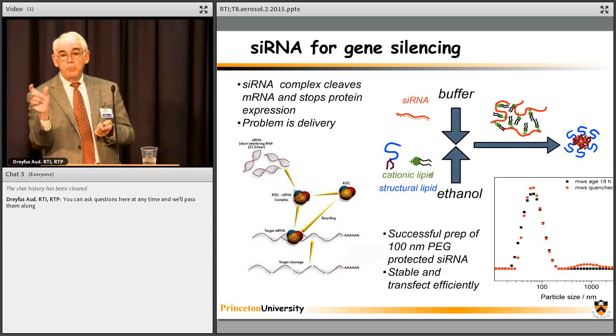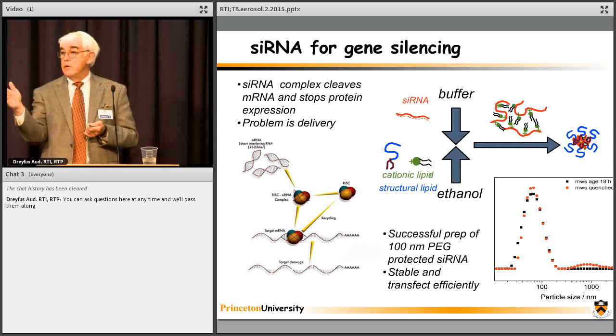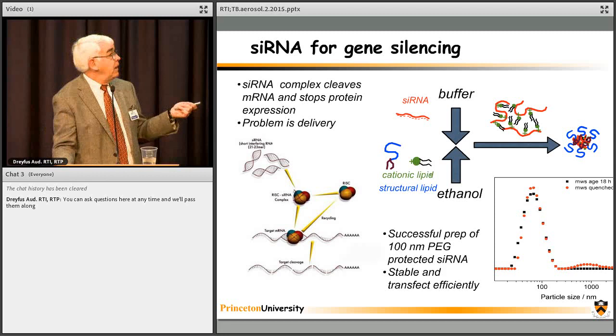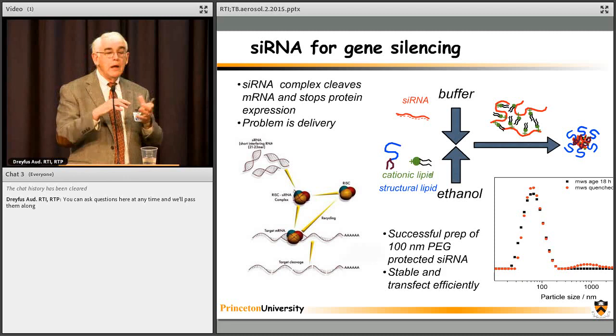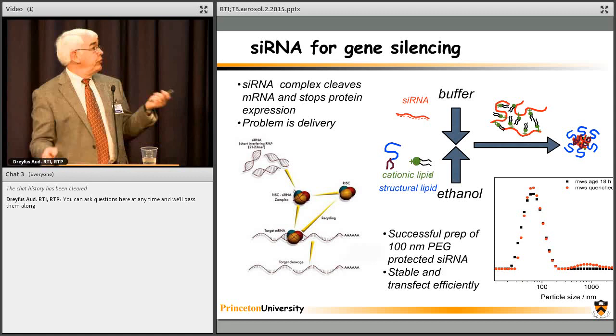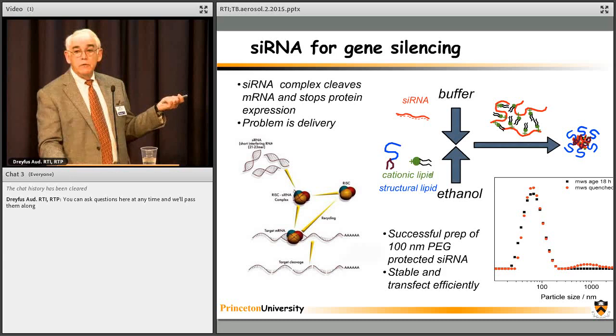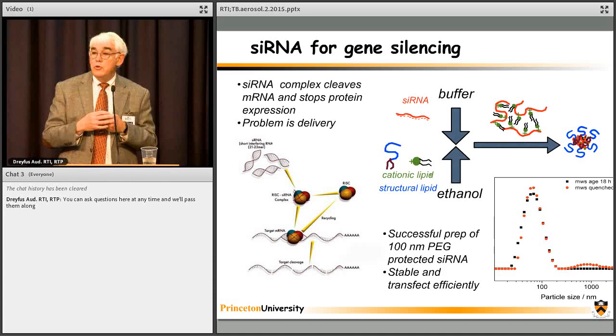a pKa of 5.2, and therefore at low pH it's cationic, but at pH 7 it's no longer cationic. You mix that with the siRNA, and then you put some part of that lipid component that has a 2K PEG tail on it. So you mix these all together, and they age into this nanoparticle over a 24-hour period. This is done at low pH, so this cationic lipid attaches to the negatively charged siRNA, and this makes it an electrostatic complex. And the question is, under rapid precipitation, could we form this, and you do not need this 24-hour aging to do it?